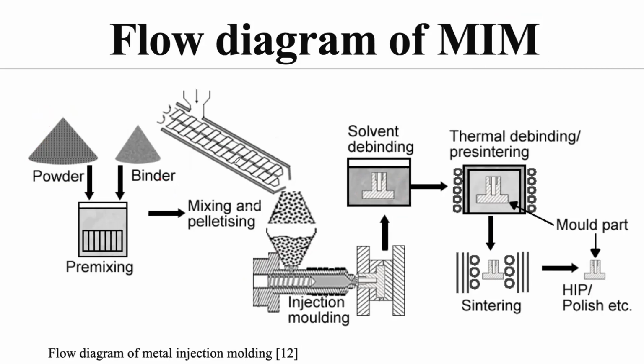So in the first step, we put it into a solvent. The solvent can be acetone, water, or any acid, and this solvent is such that it will eat away a specific material from this recipe. So it will either eat away your thermoplastic binder, or surfactant, or thermoplastic elastomer, whatsoever. But it will not eat away everything together, because then your part will collapse. So partial eating will be done and partial material removal will happen. This is also good for you, because when the partial removal happens, it creates some channels on the way.